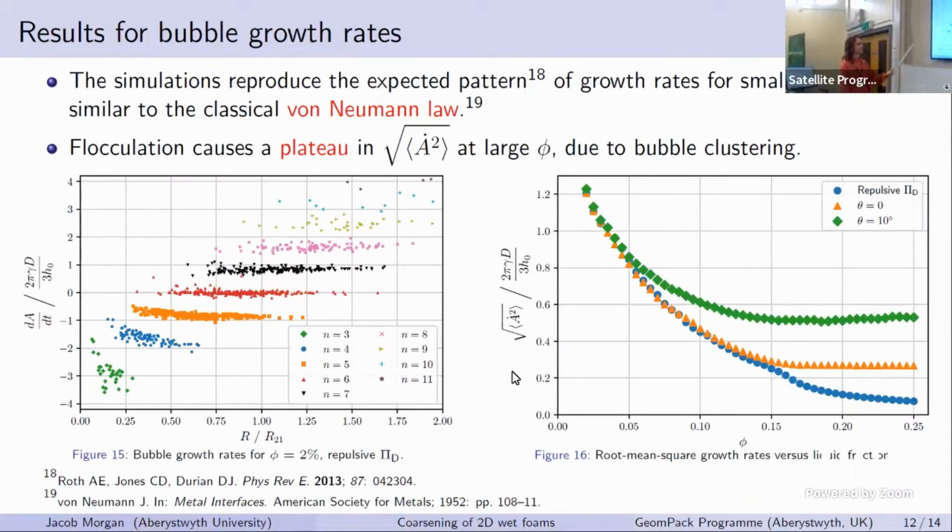So I should maybe mention that this sort of plot isn't representative of foams of higher liquid fraction. The geometric constraints that give rise to the von Neumann law break down as plateau borders are no longer meetings of 3 films, but can be meetings of 4 films and higher, and one then fills in the gaps between these levels as a result of bubbles losing neighbors. And in fact, one can see one instance of that already, even at 2%, which I checked earlier today to make sure it was what I expected. That is a six-sided bubble that is very nearly in contact with a very small bubble that is therefore supplying it with a lot of gas, and therefore it lies within the n=7 level.